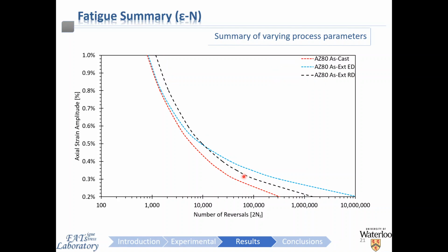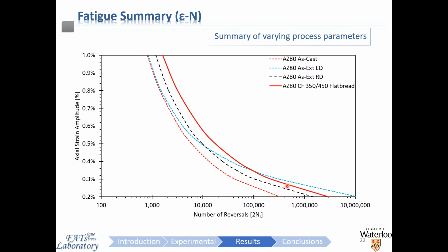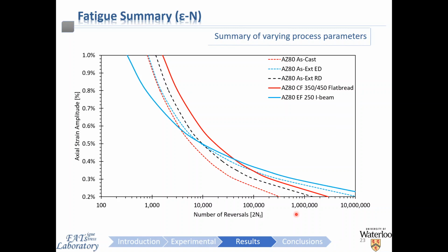In the strain life behavior, the curves vary between the extrusion and the radial direction for the exact same material. So that's important to note here, the ED and RD directions of the extruded material. Next, adding the as cast open die forged material curves, we can observe the dramatic improvement being realized, especially in this low cycle regime. So, but fairly much across the board.